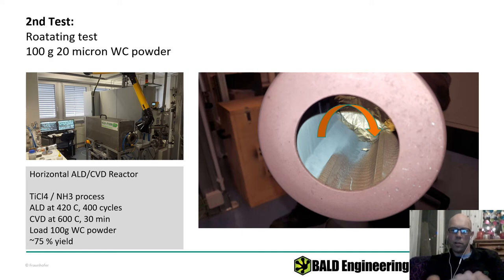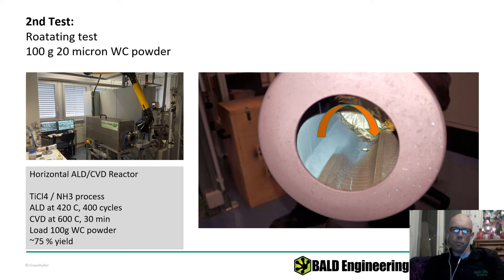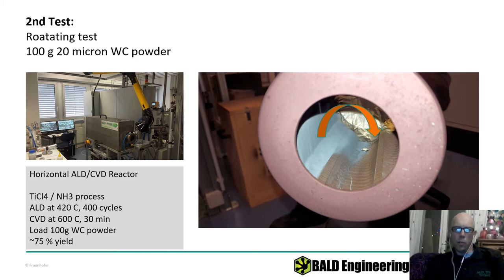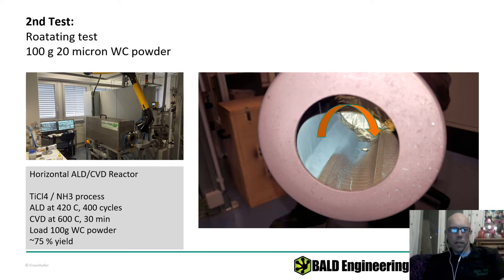TiCl₄ pulse, purge, ammonia, purge. Originally the back of the drum was open, but we've covered it with nickel foil because we were losing too much powder. Now we pulse into the chamber and suck out the gas. It's not really optimum — we have some filtering ideas to optimize it further — but with this foil we have about 75% yield, losing 25% of the powder toward the pump.